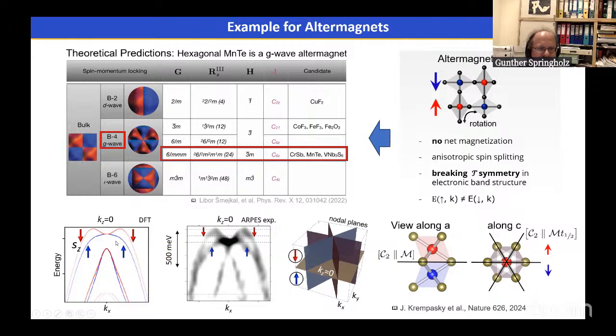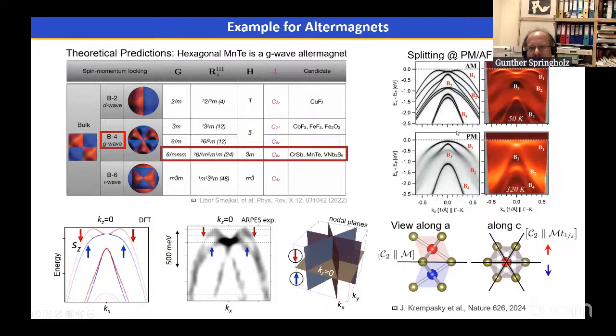So here in the lower part, it shows some calculations for manganese telluride, the spin splitting according to DFT calculations, and next to it are some angle-resolved photoemission experiments done in our group that show the spin splitting that is theoretically predicted. And we have also looked at the temperature dependence, where one can see that at 320 Kelvin, above the Néel temperature or critical temperature of the system, the bands are in the paramagnetic state. These bands are not spin split, whereas if we cool down to low temperatures to the altermagnetic state, the bands become spin split due to the altermagnetic effect.